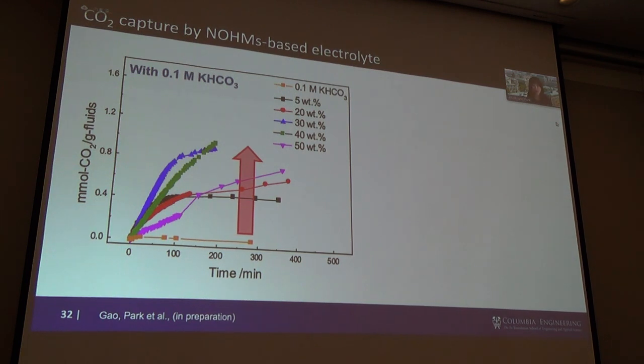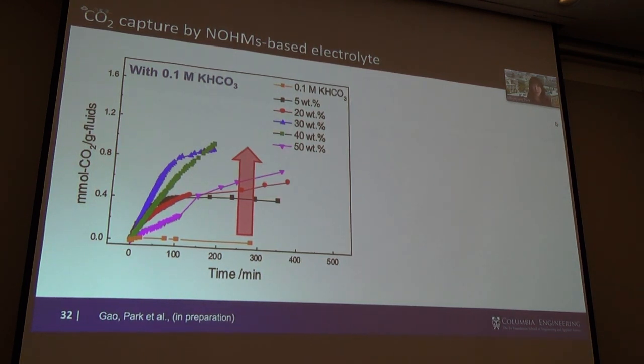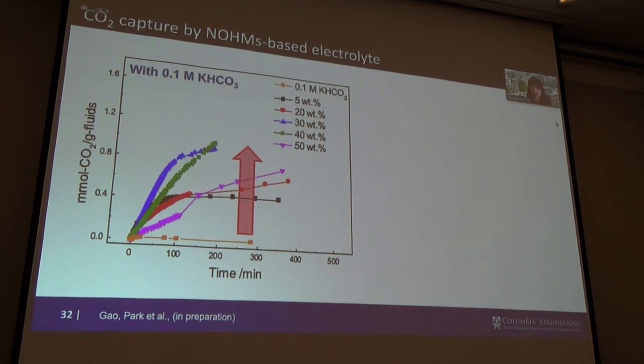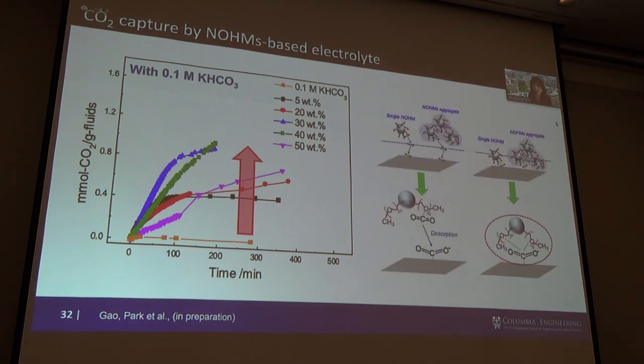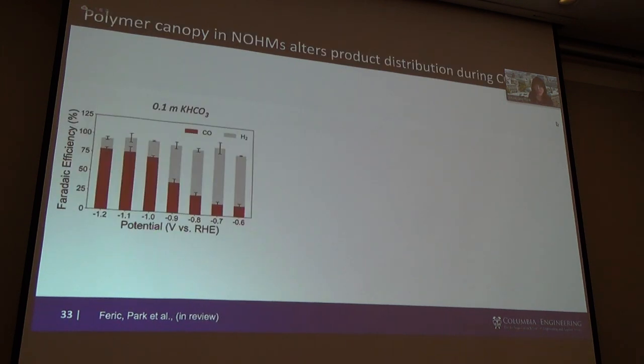Once we put this CO2 in these various electrolytes, as you can see, the orange data is regular electrolyte with just potassium bicarbonate. And as we add more NOMs into the system, we have a hugely increased CO2 concentration in our electrolyte. We hypothesized that not only do these NOMs become an internal reservoir of CO2, but they also maybe act as a co-catalyst. So NOMs actually deliver CO2 to the surface of the catalyst and bend the CO2 just right so that its reactivity and reaction pathways may change. And in fact, we did see it.